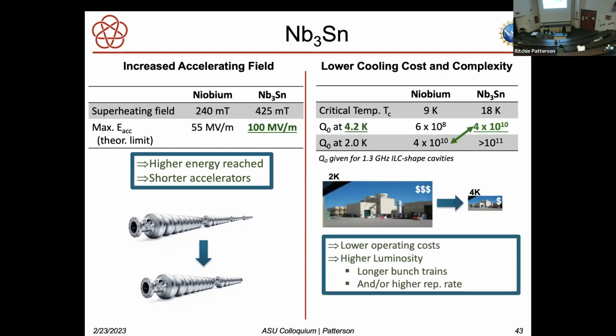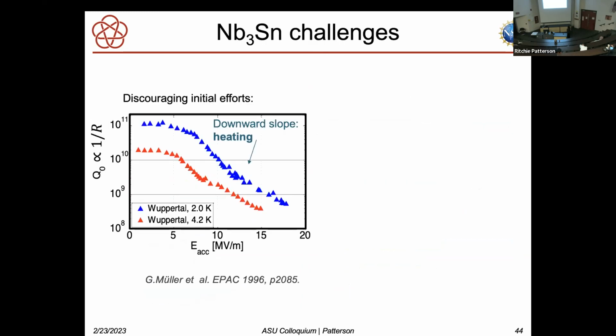You also want lower cooling cost. And for that you want a higher critical temperature. And that critical temperature for niobium-3 tin is about twice as high as the critical temperature for niobium. And so that means that you can get higher Q. And maybe most interesting is that you can get about the same Q quality factor at 4.2 Kelvin for niobium-3 tin that you would at 2 Kelvin for niobium. So that's a big win in cooling costs.